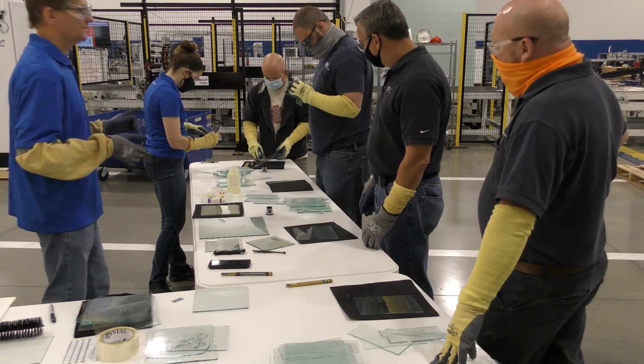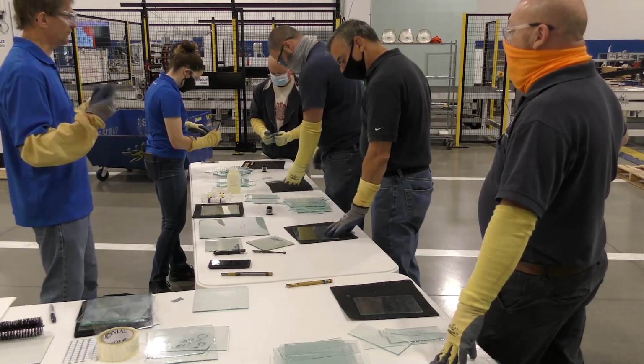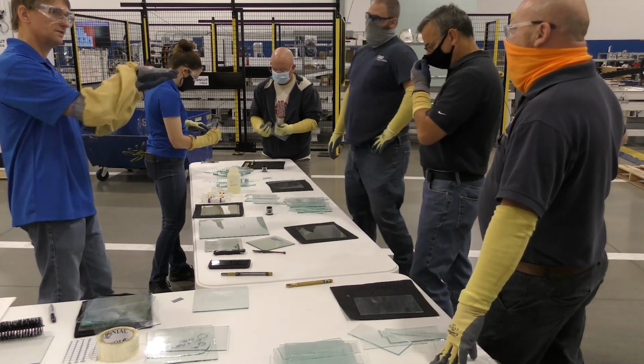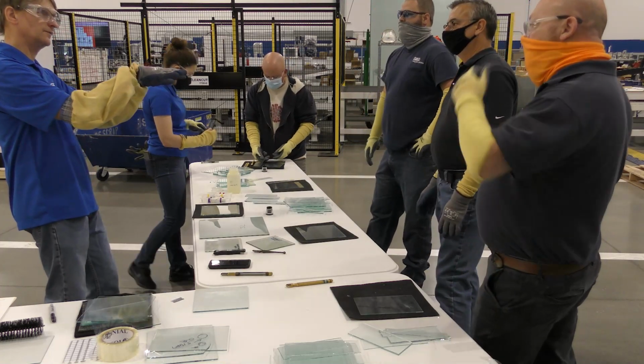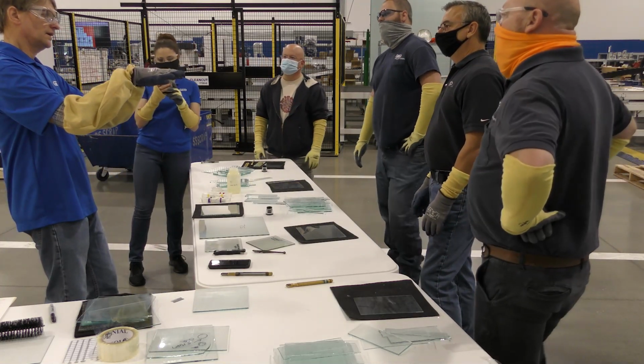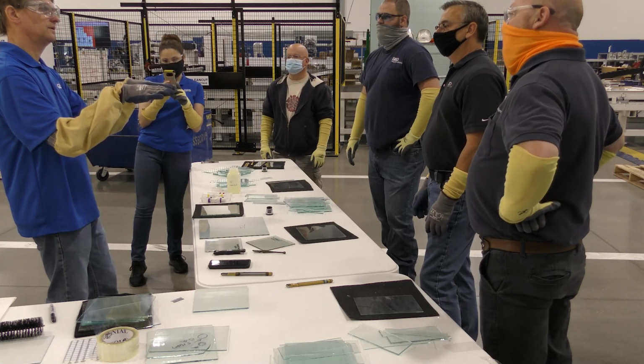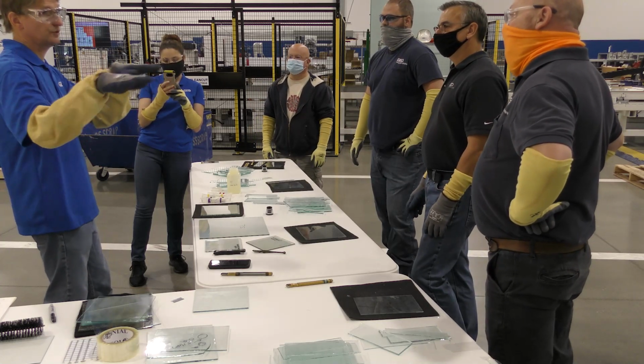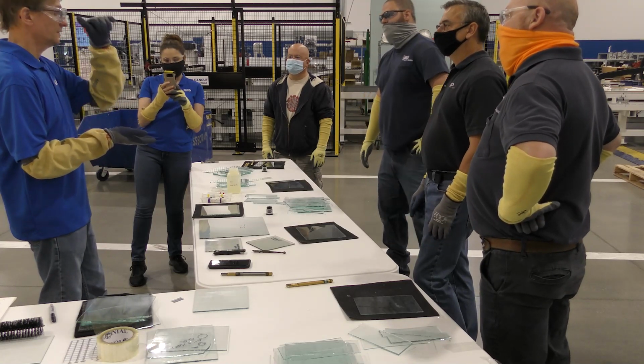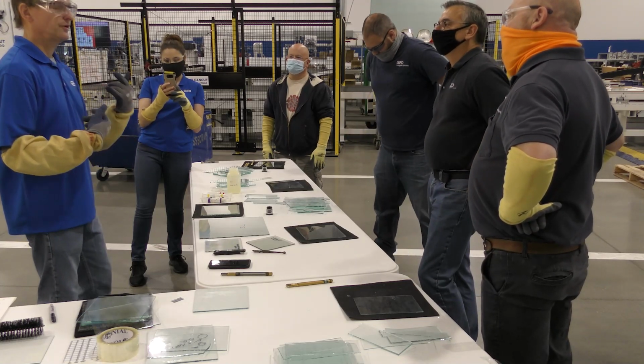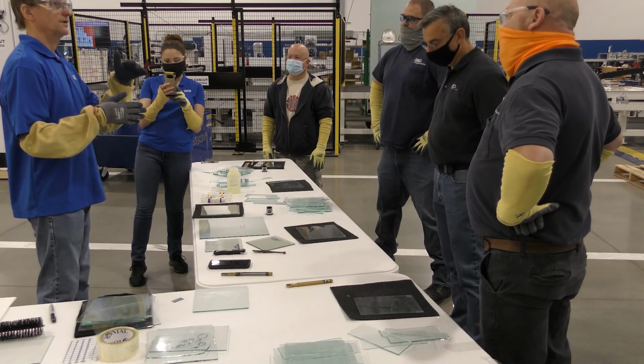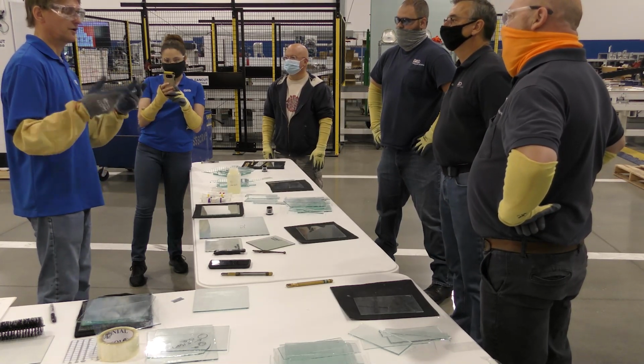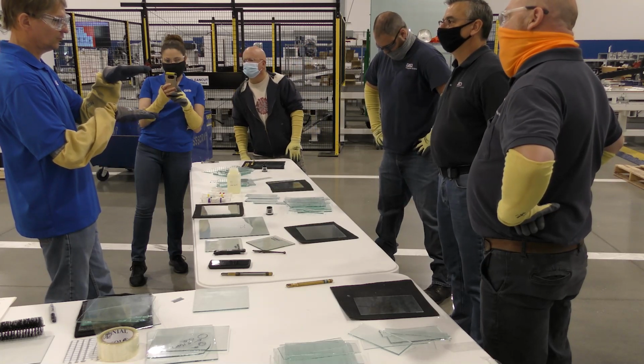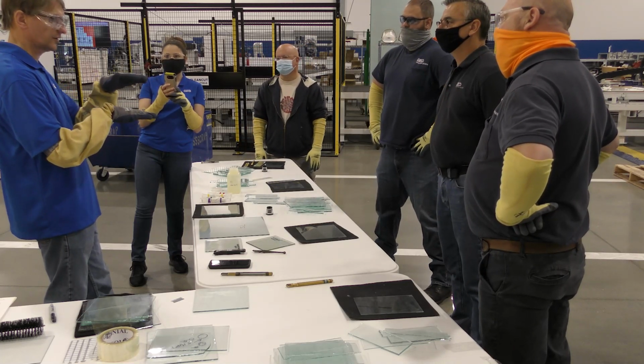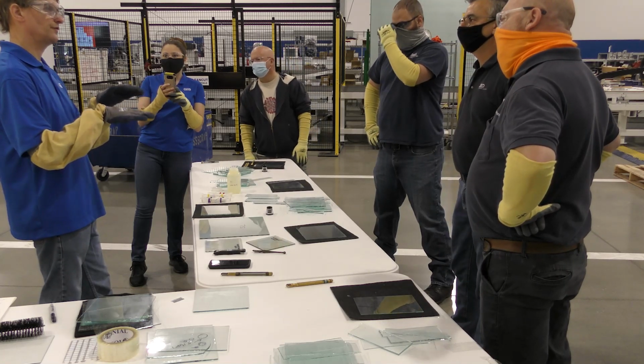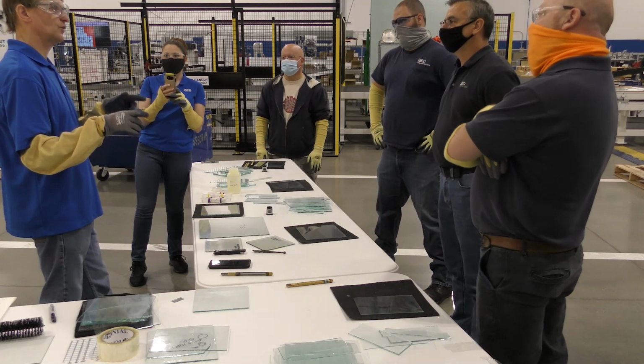Okay. Here's the deal with 2.5 mil glass, and it's different. It's really thin glass, and when I said it goes through the float line, it doesn't take as long for it to cool or anneal, cool down, as it does for thicker glass. So 2.5 mil glass cools quicker. It quenches quicker, and thus it more quickly builds a thicker compressive layer than 3 mil, 4 mil, 5 mil.